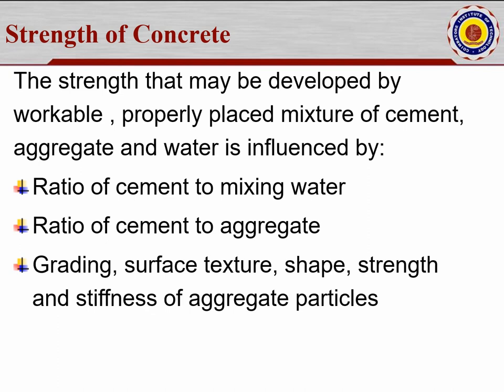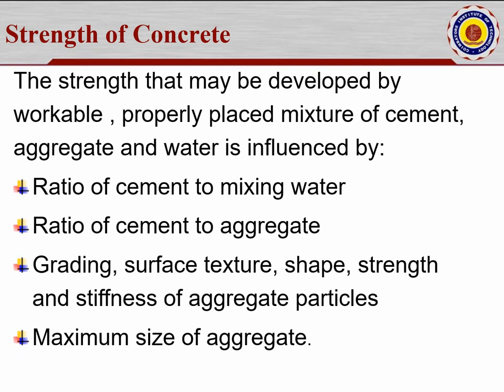Grading of fine and coarse aggregates as per IS 383 conditions is important, along with the surface, shape, strength, and stiffness of the aggregate. Initial tests should be carried out so that grading and materials satisfy the conditions for use in the project. The maximum size of aggregate depends on the type of structural element — normally 20 mm for slabs, and 20 mm or 12.5 mm for columns, to ensure durability and workability.